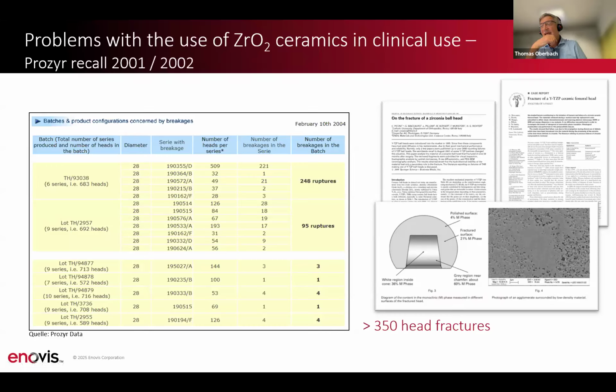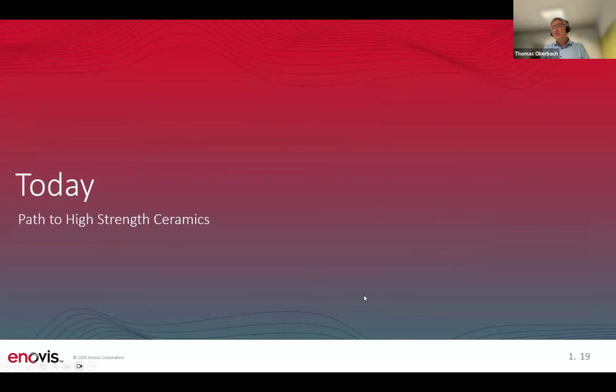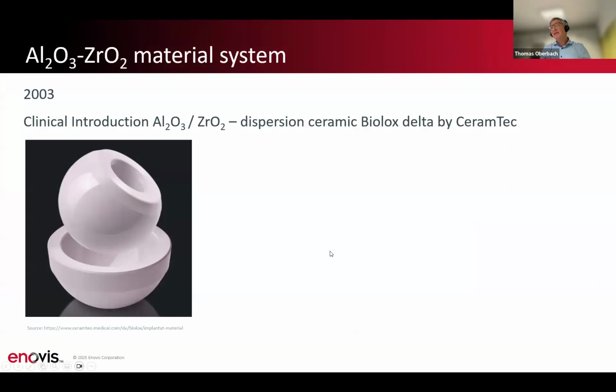This wasn't detected after the production, and after 1 year or 2 years in vivo in clinical use, they had fractured due to phase transformation and also crack propagation from the microcracks or from the micropores, and so more than 350 head fractures were documented, and this was a cut in the field of using ceramics in joint replacement. So at the moment, and I think also for the next years, there is no possibility for using pure stabilized zirconia ceramics in this market, and that's why the manufacturers looked for what ceramic materials can be used.